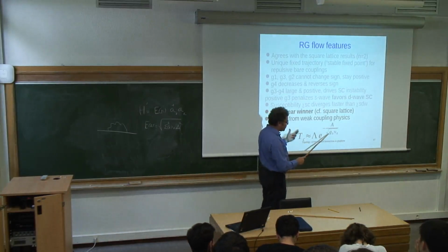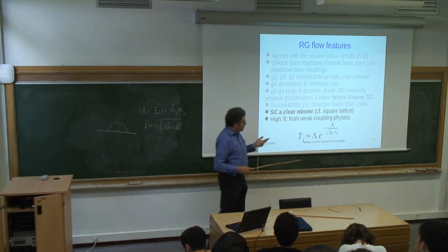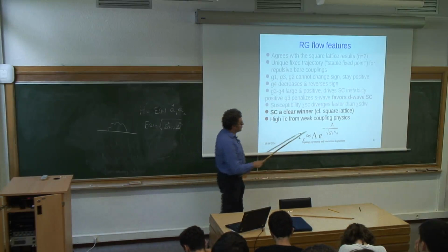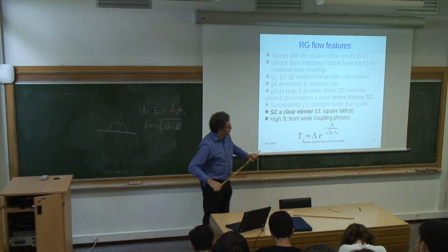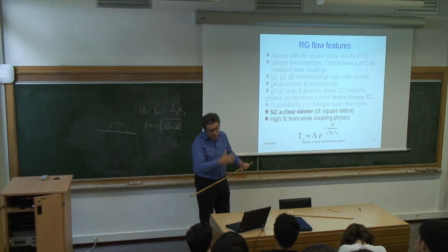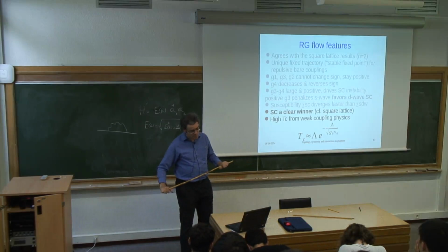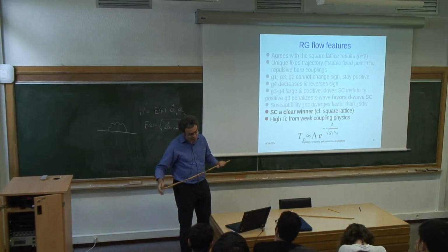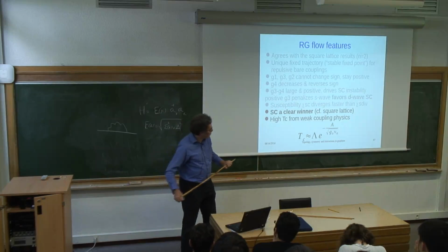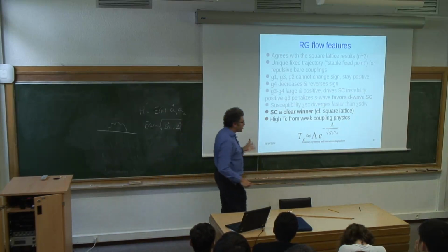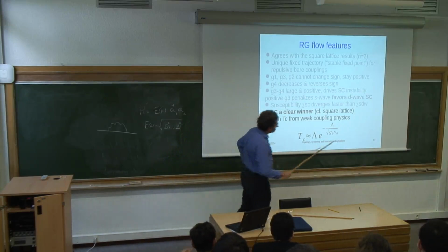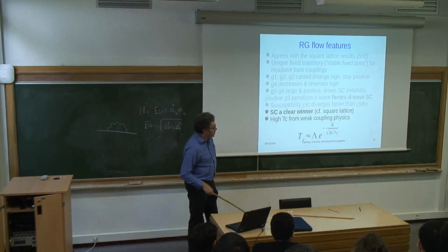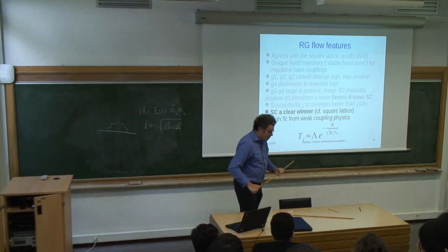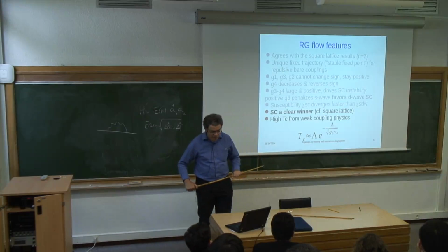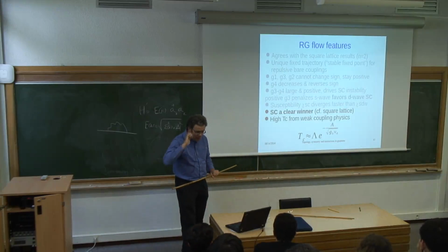And the square root, if coupling is weak, will make this much larger than without a square root. And so in this way one can access superconductivity which is purely Coulomb interaction induced, and because of that the prefactor is not over the Debye energy but over the bandwidth, and also the coupling strength is entering under a square root, and so the exponential suppression is not as dramatic as for BCS. Okay, sorry, it took too long to answer that.